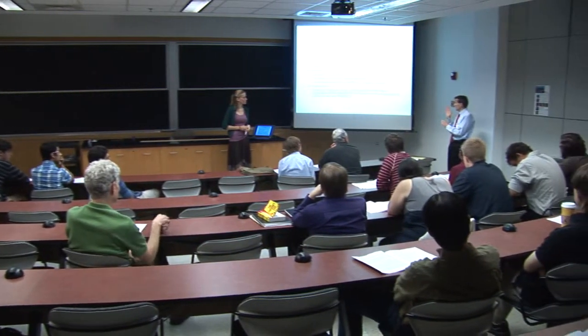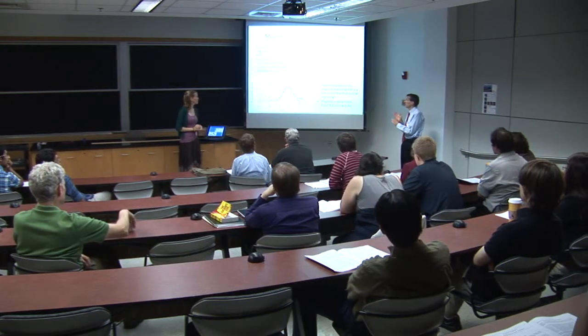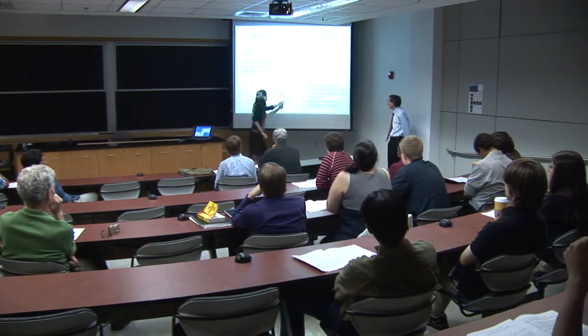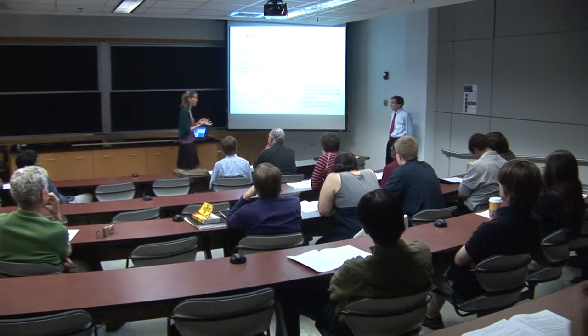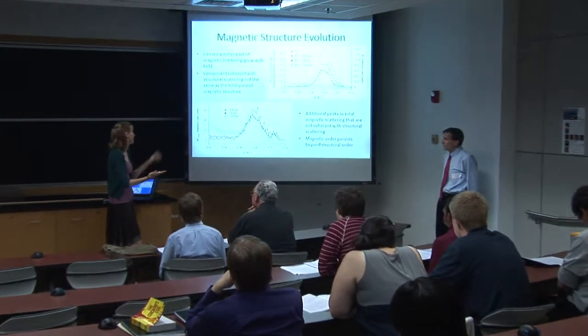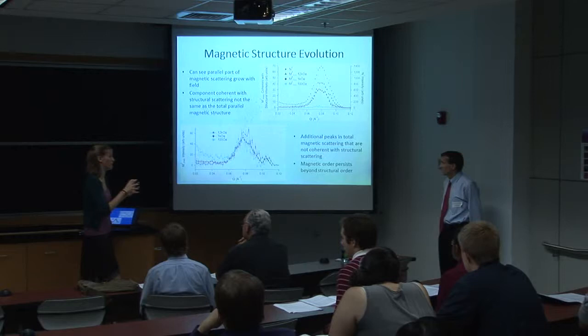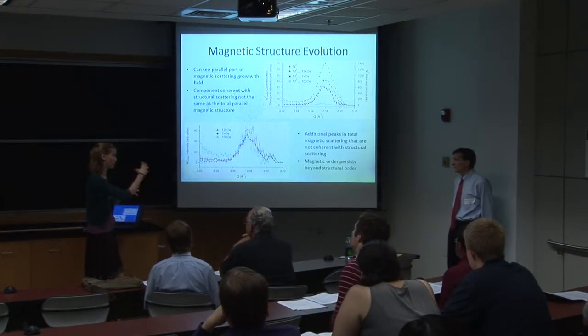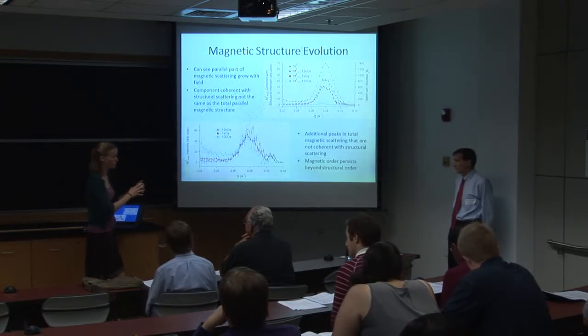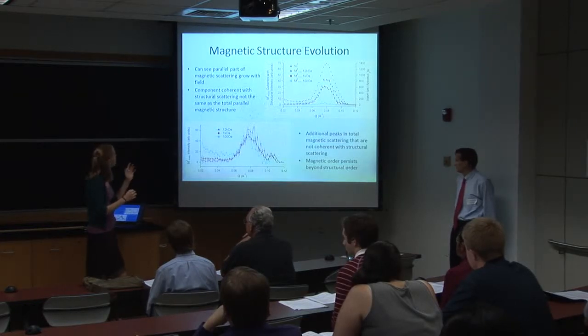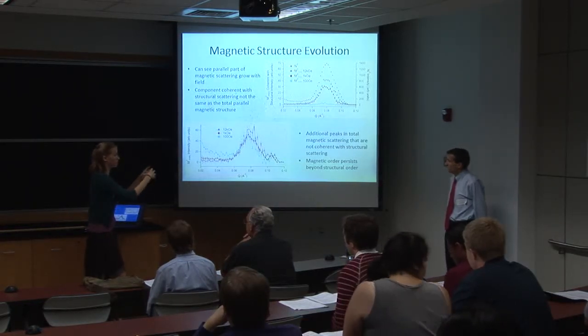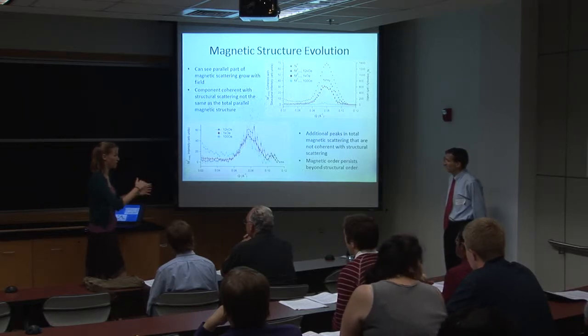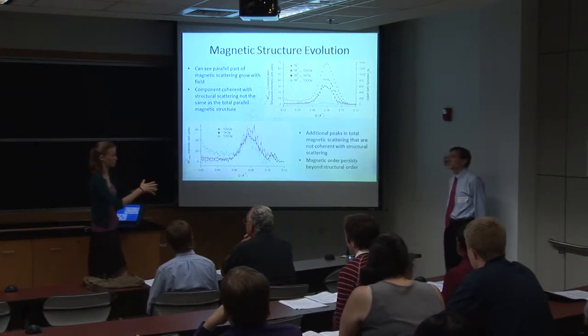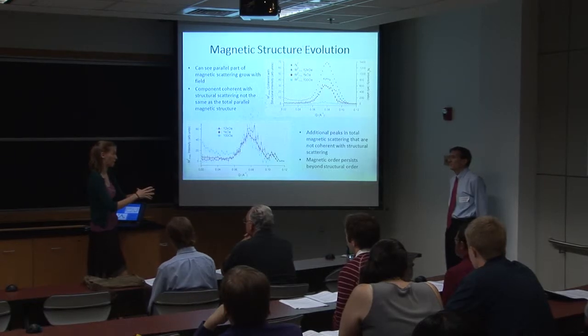And does it mean that that extra structure you're seeing is a larger cube in the last picture? So we're allowed to think that there's something spatially happening on a shorter length scale because of that larger cube? This peak? Yeah. We're thinking that there might be actually in the magnetic ordering that the magnetic nanoparticles are working together, because that peak isn't in the structure. That one's just the way that they're conglomerating in a magnetic sense. So we're thinking that the magnetic domains are working together in certain ways, and even though the structure is not working together as much, the magnetic domains are bunching together further than just the actual nanoparticles are bunching together. So there are bigger conglomerations in the magnetic domains than there are in just the particles themselves.